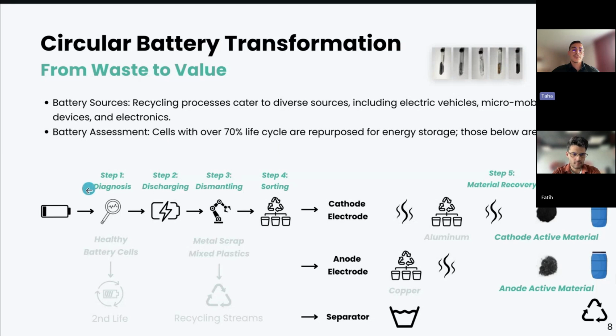For us, it is really crucial that in the first steps, when the end-of-life batteries enter our process, we do a diagnosis of each battery cell and analyze if this battery cell still has a capacity of over 75%. This is for us the critical capacity in order to enable them to go to a second life process in a stationary energy storage, because there they can live for 2 to 3 years longer, because the stress on the battery cell in a stationary energy storage is not that high. So there we work with partners and also have our own solutions to go for a second life application. If the capacities are below 75%, then the batteries enter our recycling process.